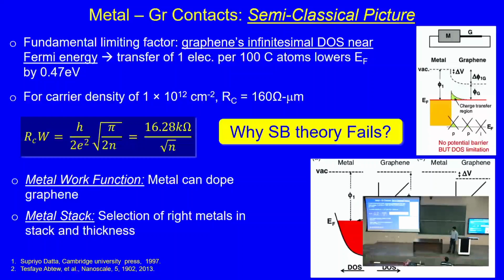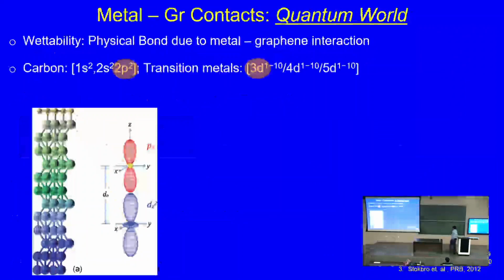What we noticed is that in case of graphene, when you lower the temperature, you actually get better contacts. Now, a lot of physicists have already reported, not this observation, but just to report better contact resistance, they had reported contact resistance at lower temperatures. But nobody questioned why you are getting a lower contact resistance at lower temperature. When you go with this theory, you should be getting a higher contact resistance. So that was one thing we questioned, and that's when we started looking into the chemical interaction.